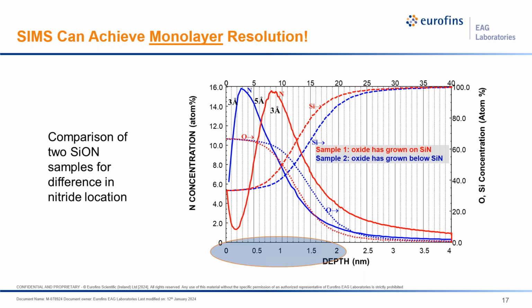This example shows a thin oxynitride, basically an oxide that has some nitridation process. Even between samples that have only a few angstroms of difference in thickness as well as nitrogen position, we can resolve those differences. So keep in mind that your thin film can still be quite thin, and we can still get sufficient depth resolution to provide information on your samples.